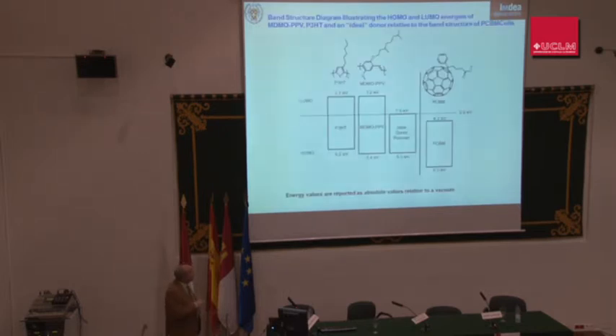Another important aspect is to consider the energy levels. This is the typical poly-3-hexylthiophene. This is a paraphenylene-vinylene derivative. These two polymers have been by far the most typical polymers used for photovoltaic devices, and PCBM has been the best studied molecule as well. But if we want to prepare an ideal donor polymer, we have to control the HOMO and LUMO levels. What could be considered ideal is a gap energy between the HOMO and LUMO of around 1.5 electron volts. So this is considered a low band gap polymer, 1.5 or lower, typically.